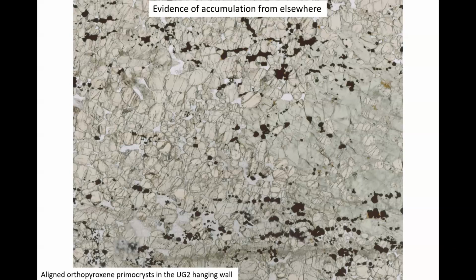Thank you very much. I was wondering if you've ever used EBSD to look at whether you've got distortion and misorientation at the chromite interfaces. I probably missed that bit of the literature. Did you mean the grain boundaries or deformation within the chromites? If they've been interacting while connected, you would expect to see different things at the chromite interfaces, in the grain boundaries, like the different coincident site lattice boundaries as well, not just twins. We tested twins and how common they are. There is no systematic pattern. Excellent.